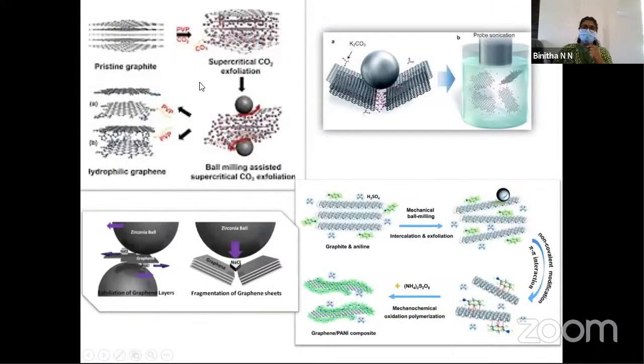Another exfoliating agent is PVP in the presence of supercritical carbon dioxide. And even inorganic salts such as alkali metal salts, potassium carbonate, sodium carbonate, etc. can be used for the exfoliation of graphite. One graphene polyaniline composite is prepared by ball milling graphite with aniline in the presence of sulfuric acid. After that, the ball mill mixture is subjected to mechanochemical oxidation polymerization for the preparation of graphene polyaniline nanocomposite. So in situ preparation of nanocomposites is also possible by ball milling.